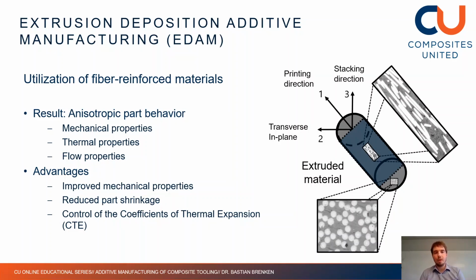and you then can conclude the print. Another interesting aspect is that by adding short carbon fibers, you can control the coefficient of thermal expansion of your tool, because as you can imagine, if most carbon fibers align parallel to the printing direction, the consequence is that your CTE in this direction is very low. So at least layer-wise, depending on how you orient the layers, you can control how your tool is going to expand in a later heating cycle.